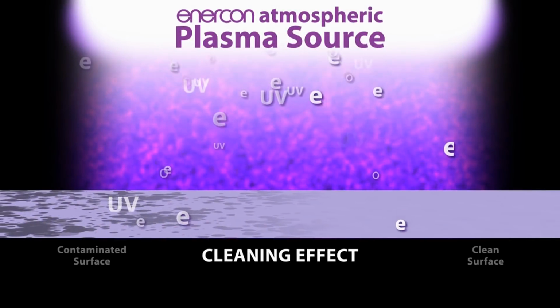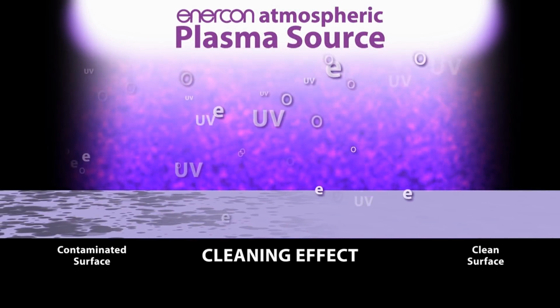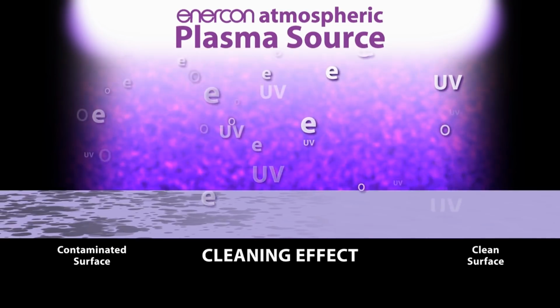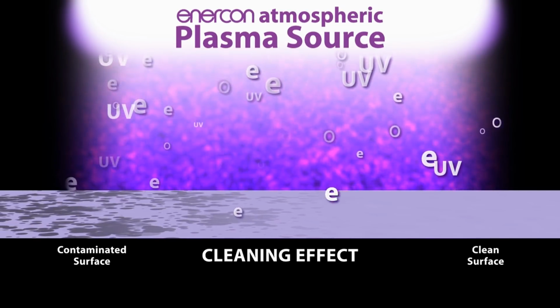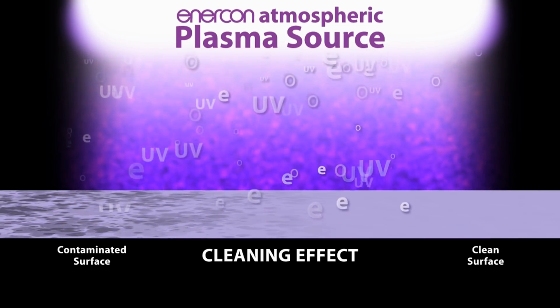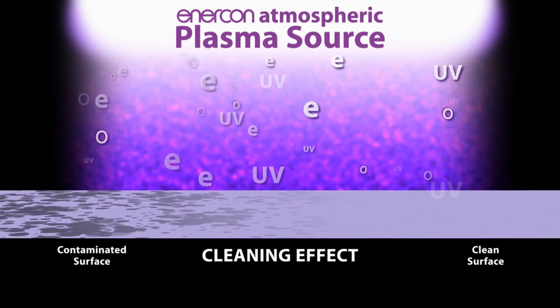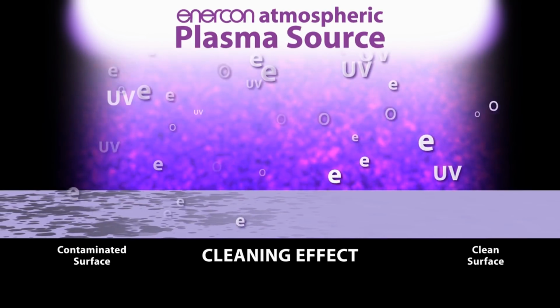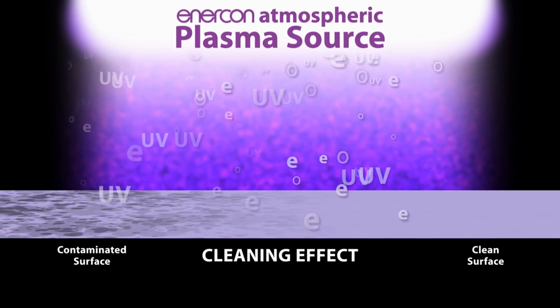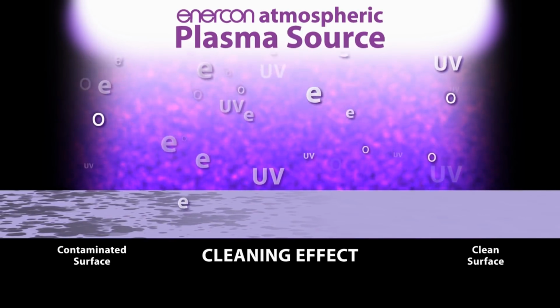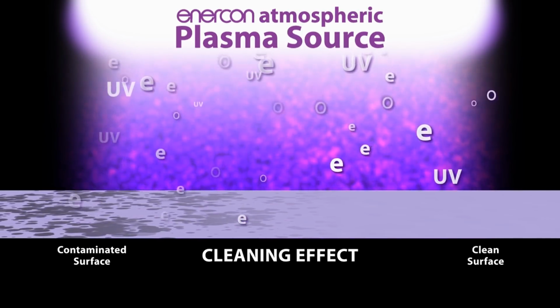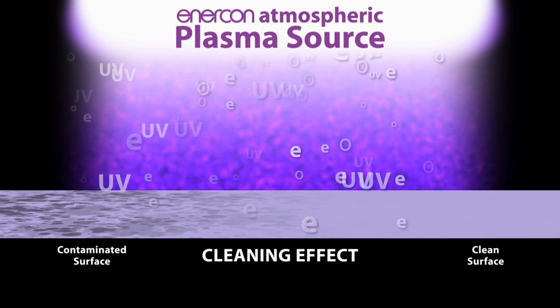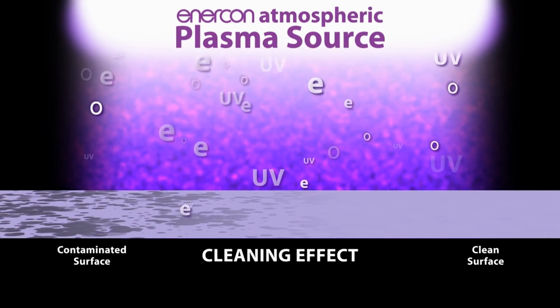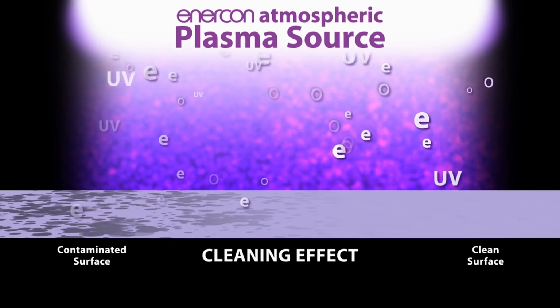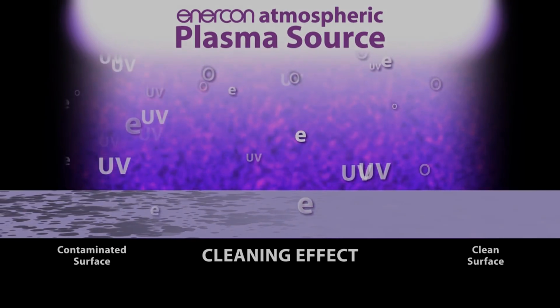Plasma will clean your surface. In this video, you will see plasma attacking contamination on the surface. Static charges are eliminated, so any dust or other materials held on with static are removed. Plasma also removes most organic and some inorganic contamination. As for organics, hydrogen and oxygen ions in the plasma combine with the hydrocarbons of organics to produce carbon dioxide and water vapor. Removing inorganics can be more difficult and usually requires more aggressive treatment or longer cycle times.